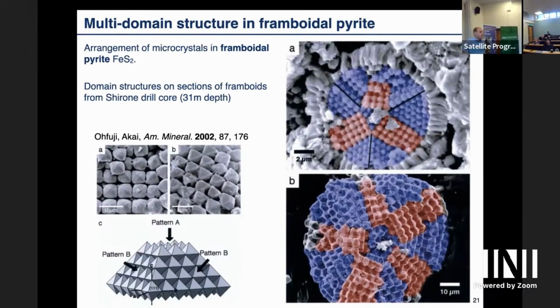So now we are going a little bit away from the polydispersity. And if they are in here, they look a bit like octahedra, somewhat common. And this shape is actually the Wulff shape, so that has to do with the crystal structure. In this case, it's FCC, or yeah, it's a binary because it's sulfide, but essentially you can get the same with the FCC structure. Here they are more like a bit truncated octahedra.